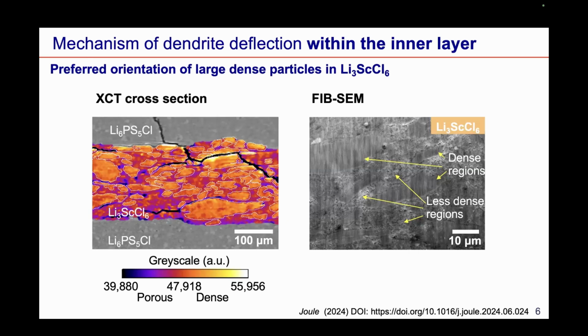You can also see these large dense particles. It also should be noted that these large dense particles are preferentially oriented with their long axis parallel to the interface between these layers. These dense particles will influence the propagation pathway of the dendritic crack. Indeed, you can visualize that the dendrite crack deflects along the boundaries of these dense particles. So we can conclude that it is these dense and stiffer particles with preferred orientation that deflect the dendritic cracks within this inner layer.